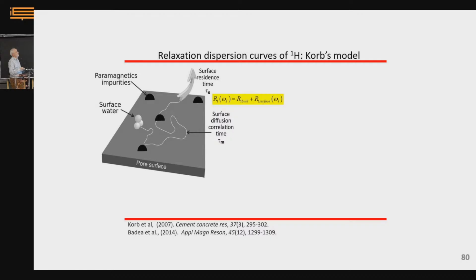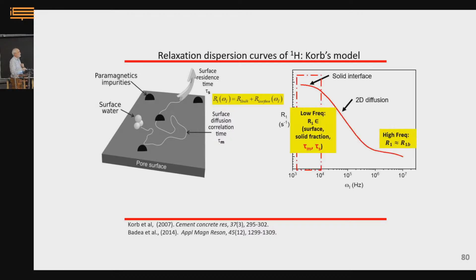Because relaxation of your proton in water is actually a sum of two phenomena. One that occurs in the bulk, due to the fast reorientation of the molecule of water. And because this reorientation is very fast at the NMR time scale, with the frequency we are probing by NMR, it is frequency independent. But when the molecule of water is adsorbed on the surface, its motion is constrained by a 2D diffusive path on the surface, and it becomes frequency dependent. So through the analysis of this frequency dispersion of the relaxation rate, we gain information on the diffusive path on the surface with characteristic times associated to this process. But I won't tell you the whole story because I don't have time.